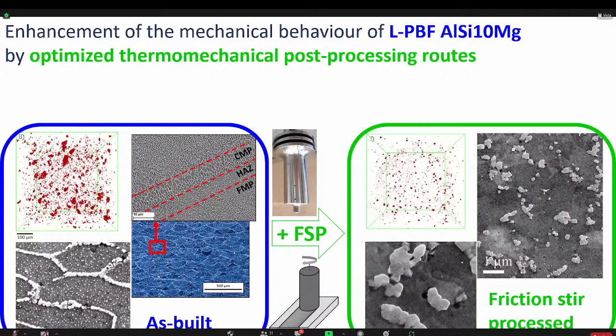The resulting microstructure is the following. First of all, in terms of porosities, you can see a significant decrease in the amount of porosities after this process. You also have a more homogeneous mesostructure. As you can see here, you have no more melt pool structures. However, you have a growth of the microstructure and a complete globularization of the silicon network that was typical of the as-built material.